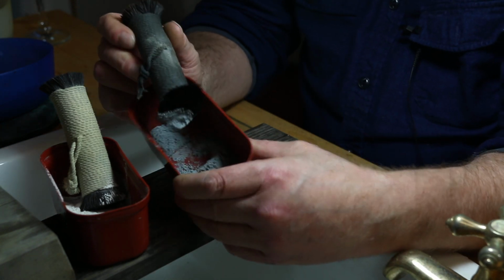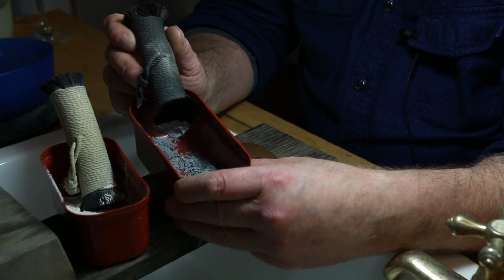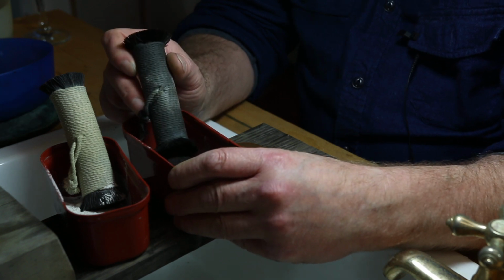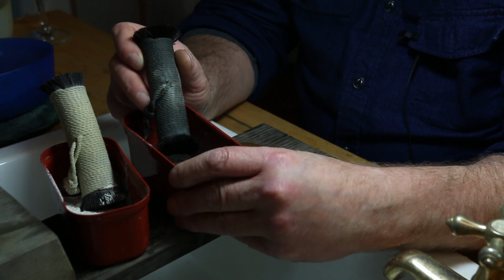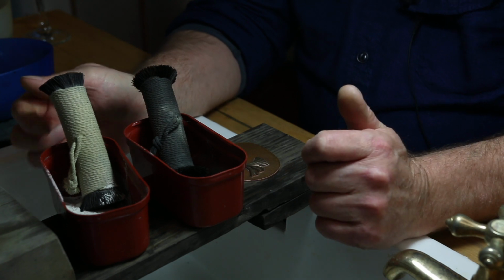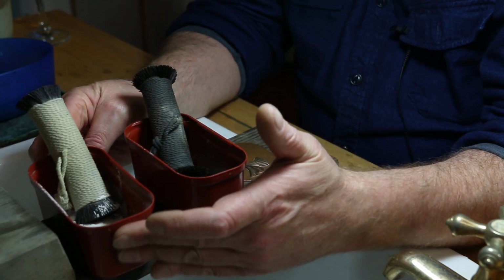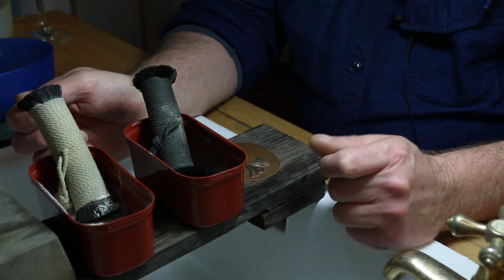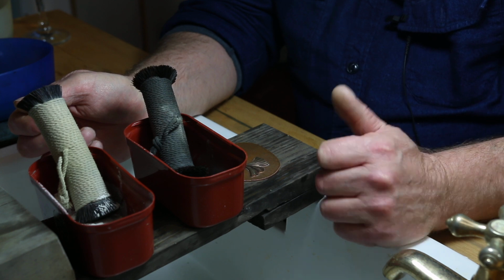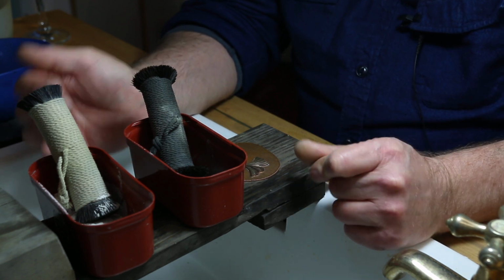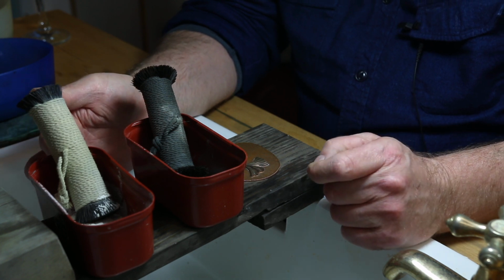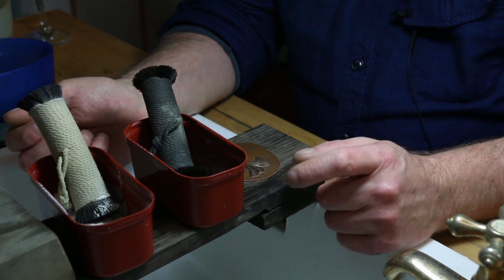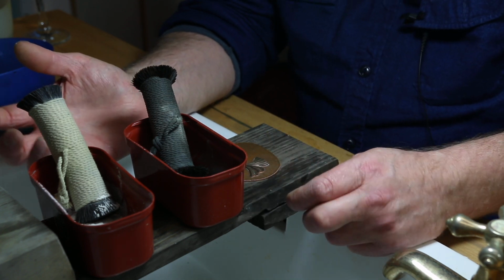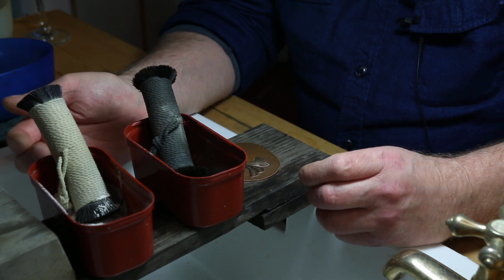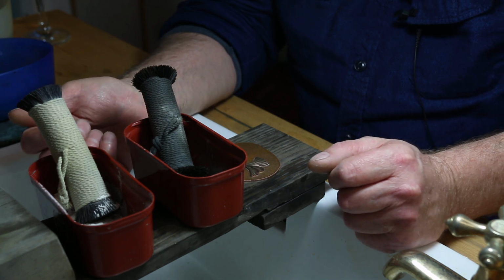The other material I used to use quite a lot when I was doing restoration work was silicon carbide. This is silicon carbide powder. It's 600 grit. This cuts very quickly, very sharp, and it'll give you more of a shiny finish. What I sometimes do is I will use the pumice powder to clean and polish, and then I will take a little bit of the silicon carbide on my thumb and polish the high spots. So I've got a nice contrast of glossy and matte. A matte finish from the pumice will show the color really quite rich, whereas a glossy one will have more reflections, but it'll have more of a wet appearance. Of course, everything is waxed, so it's subtle differences in the final finished piece.